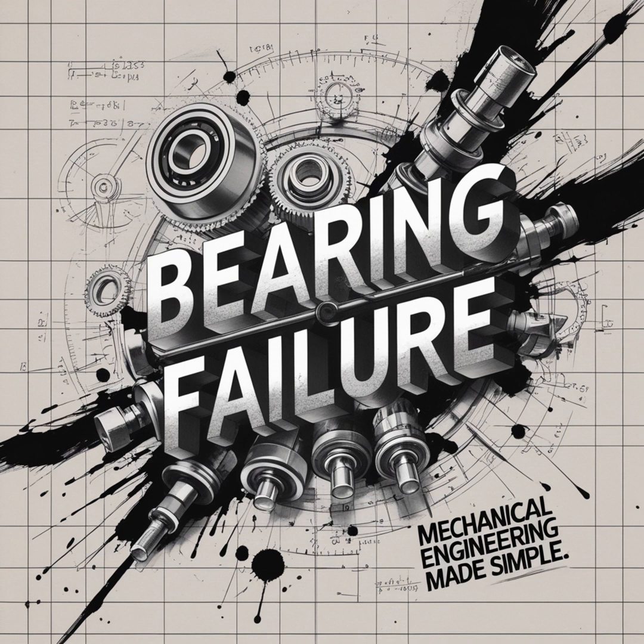You got it. Okay, moving to contamination, which you said is tied directly to lubrication and sealing. What are the two types we're worried about, and how do they damage the bearing differently? Well, we mainly deal with solid particles and liquid contaminants. Solid particles, dust, grit, little bits of wear debris, they cause indentations. Little dents, yeah. As a rolling element passes over a particle, it creates these tiny craters in the raceway. Those craters become localized stress concentrators, which is the perfect starting point for surface fatigue spalling. It's abrasive wear, pure and simple.